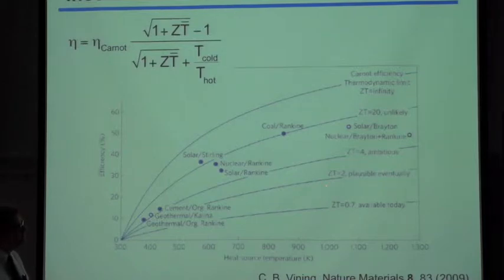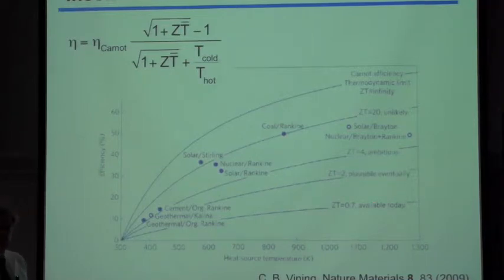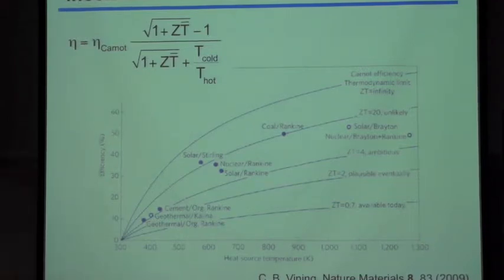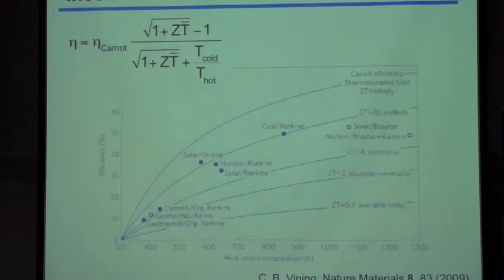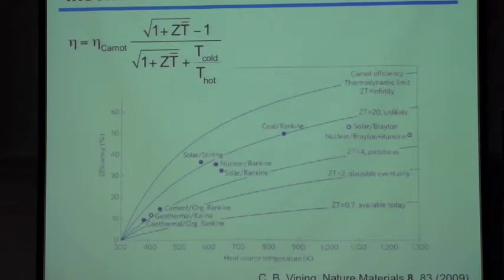Realistic values for different materials are given here. A typical material nowadays has a ZT of 0.7. In fact, the radioisotope thermal generators I described work with silicon-germanium and have a ZT, really state-of-the-art fabricated by molecular beam epitaxy, of a little above 1.1. The holy grail currently is to reliably reach a ZT of 2. But even at that goal, at a temperature of around 1000 K, you are still at a reduction of the Carnot efficiency by roughly 60%.